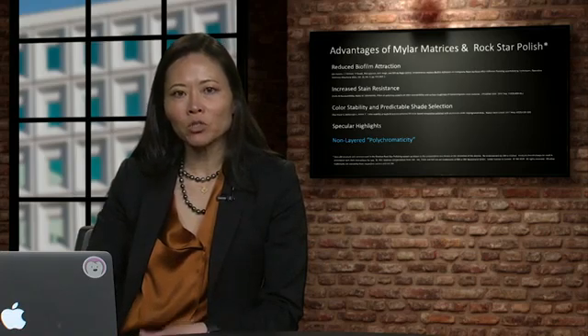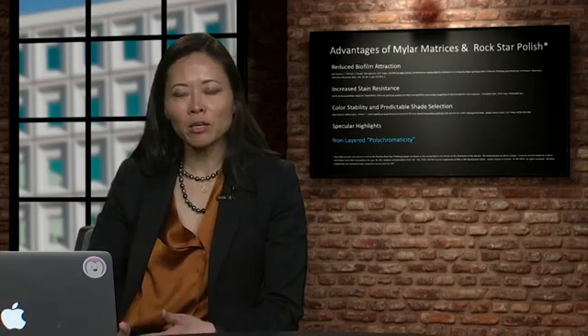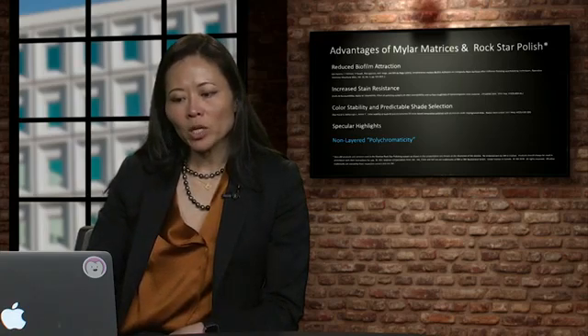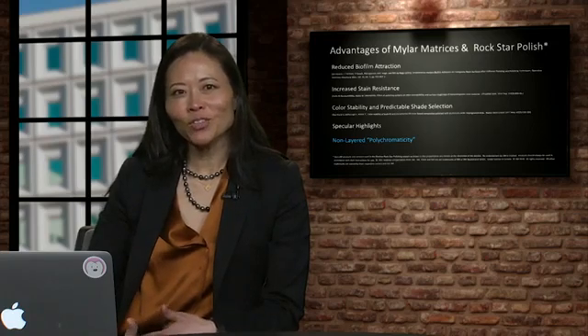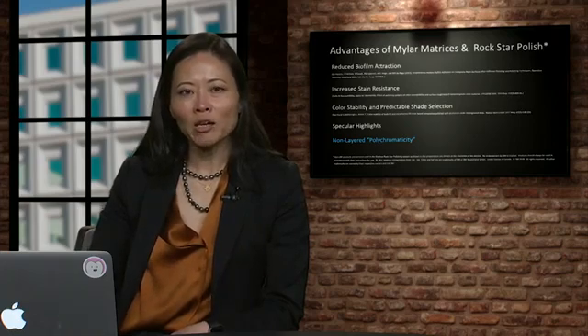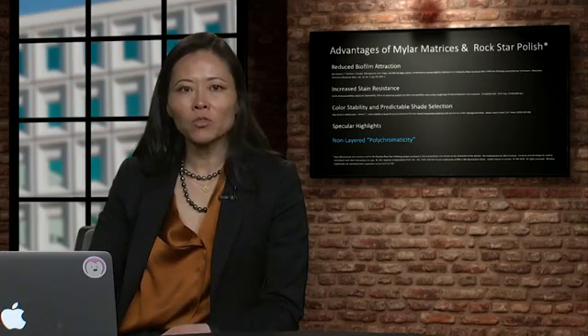So if you think about that in terms of our composite restorations, the more that we manipulate it, the more defects and the more air that we're incorporating into those composite restorations, we're actually increasing the value, and we're taking away from the natural opacity or translucency that the composite actually has. So if we don't manipulate the composite too much, and if we don't introduce a lot of air, then we get the benefits of a nice translucency that allows some of the underlying tooth coloration and character to come through. So we actually can create some polychromaticity on these restorations, but in a really safe way as far as longevity, because they're monolithic.